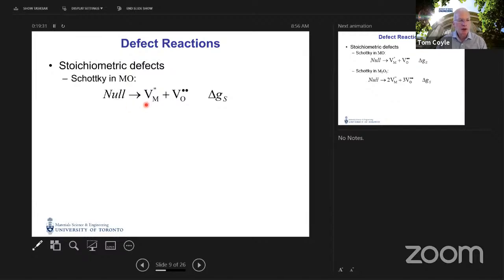So a Schottky defect consists of a vacancy on the metal site. Those metal cations ought to have a +2 charge, but that cation is missing. So that site is missing 2 positive charges, therefore has a -2 effective charge. And the other part of the Schottky defect is a vacancy on an oxygen site. That site ought to have a -2 charge associated with it, but the oxygen anion is missing. Those negative charges are missing. And so compared to what ought to be present at that site in the lattice, we have an effective charge of +2 or 2 dots.